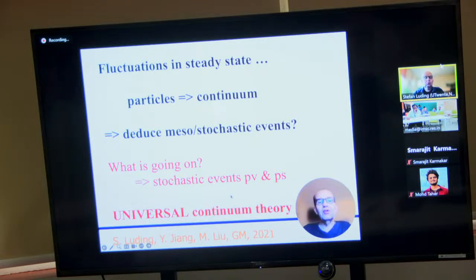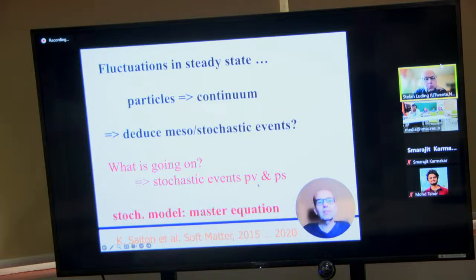Now, the universal continuum theory we published two years ago in Granular Matter, and you can read the details there. The essential pieces in the continuum theory are these two probabilities, PV and PS. And I showed you the microscopic origin, the mesoscale origin, the restructuring of the contact force network, which goes into the continuum theory. We also did stochastic modeling. We actually did that already a few years ago, and that's based on a master equation taking into account the probability densities, the transition probabilities from one state to the other. So that's a back reference. Thank you.